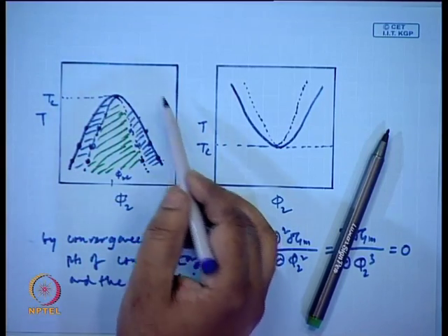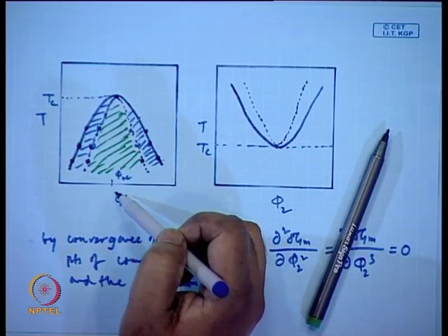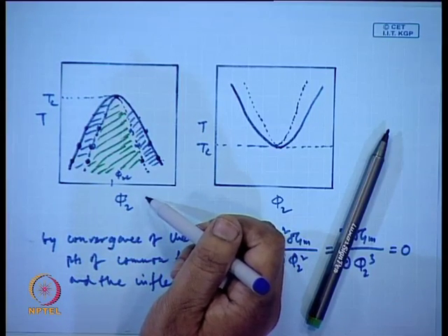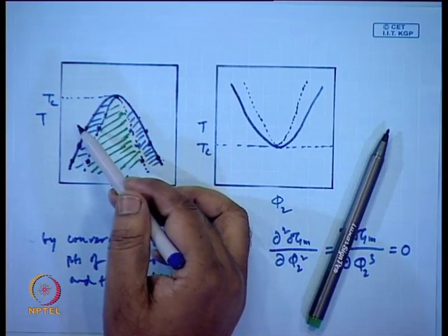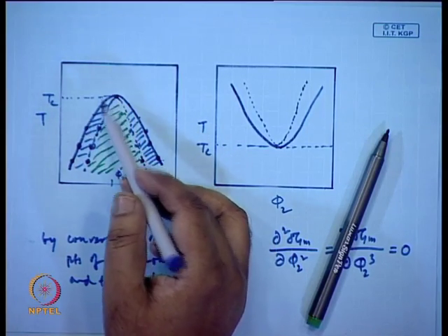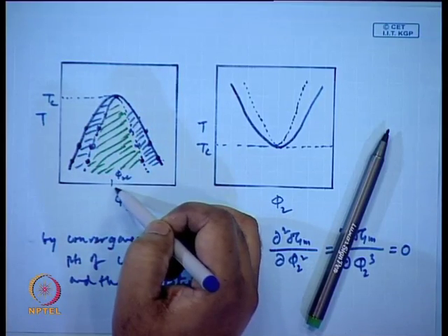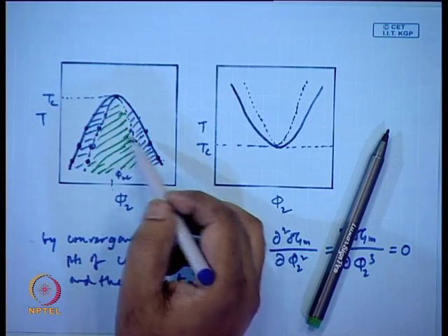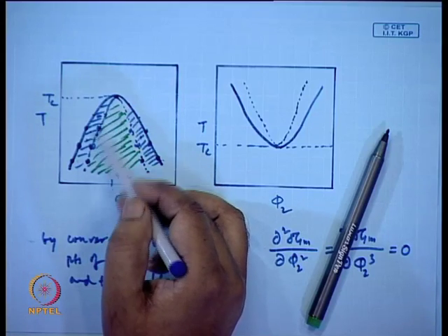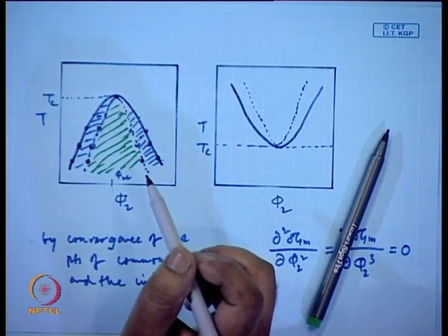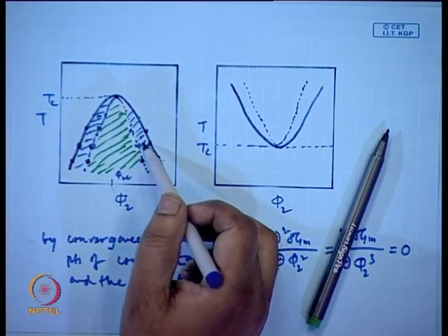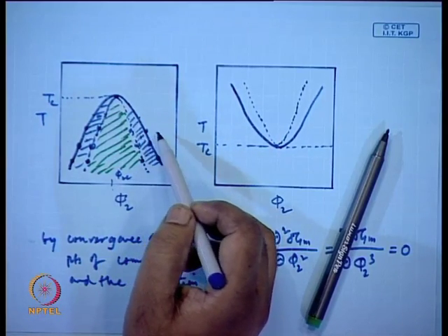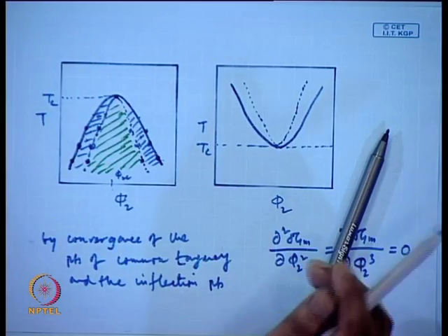So, in this simple diagram, you can get the complete phase diagram. It basically gives you the phase diagram of that polymer in that solvent. So, you are plotting the composition of the solution at different temperatures. At any point in this region you get a single phase, which is polymer soluble in the solvent. At this temperature and this composition, you get two phases, polymer and pure solvent, and in this case you get a metastable solution, which will be stable towards small fluctuations in the composition, but not large fluctuations. So, this basically gives you the phase diagram of a polymer in a solvent from that original Flory-Huggins equation.